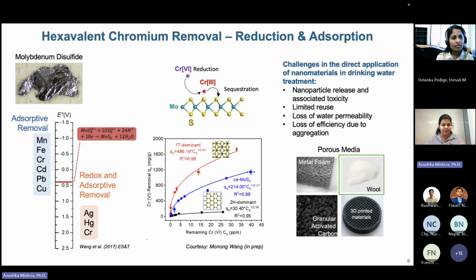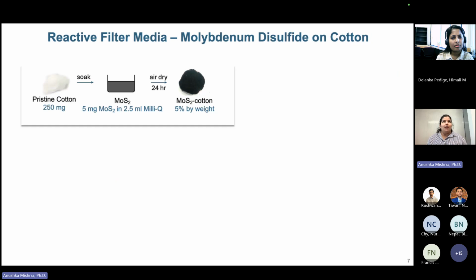So I tried a couple of different porous medias. Granular activated carbon can be a very attractive substrate if you think about it, but it itself undergoes a lot of reactions with the molybdenum disulfide, so it didn't really work well. But if you have something like a wool, it can be a mineral wool or cotton wool, we start seeing some interactions between the nanoparticles and this material. And the best that worked for me was cotton wool.